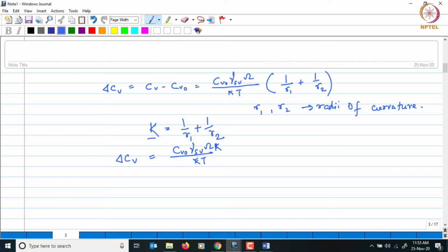Now when you apply pressure during hot consolidation, the vacancy concentration under the neck surface is not affected, and therefore following a similar approach, we can write this expression for the vacancy concentration difference in this case, where CVN is the vacancy concentration at the neck surface.